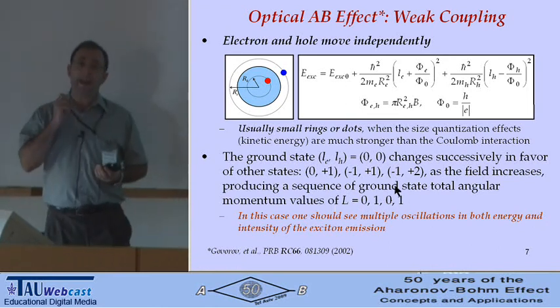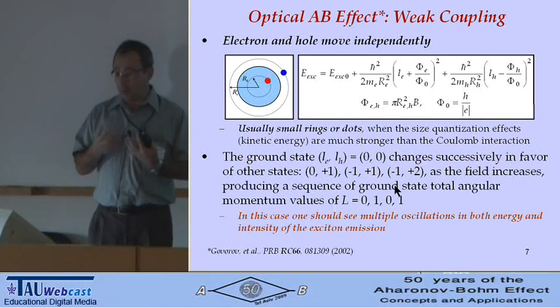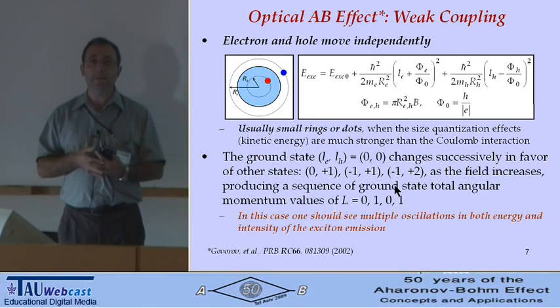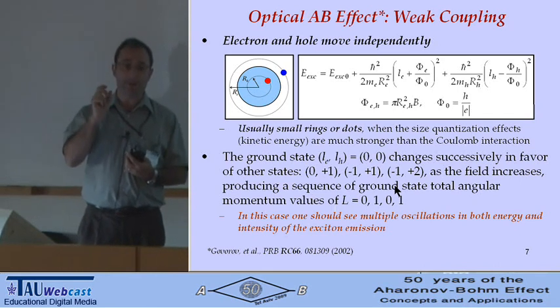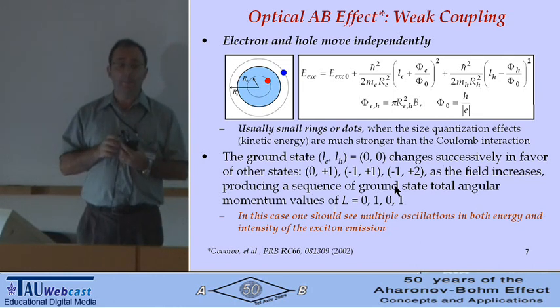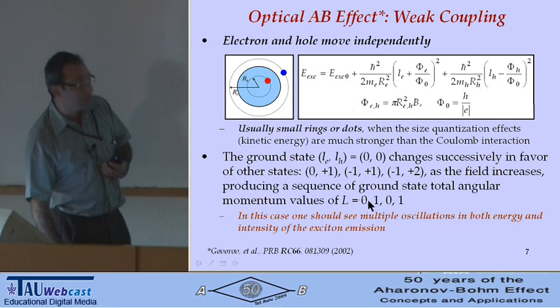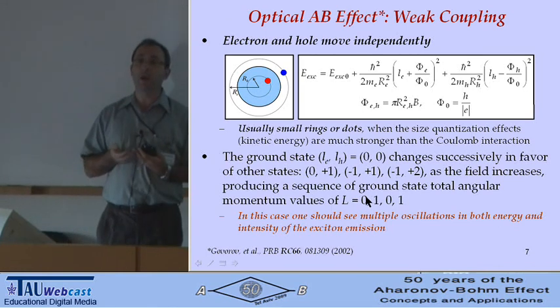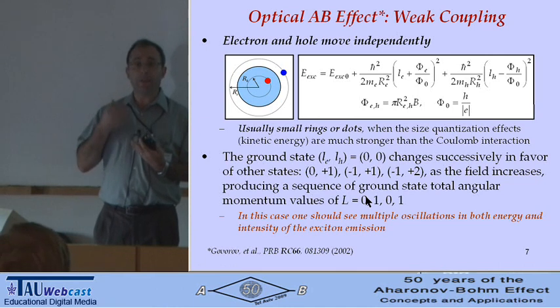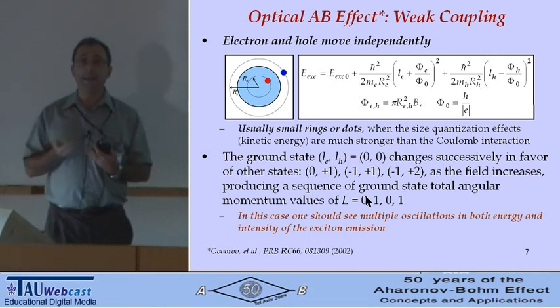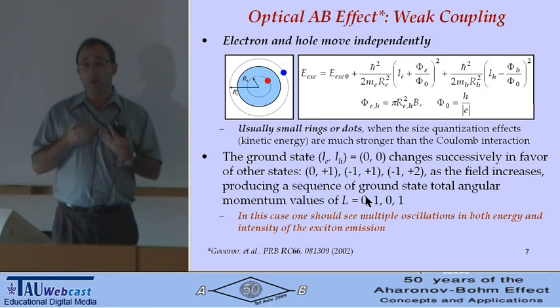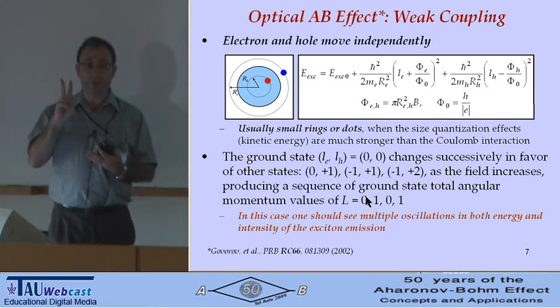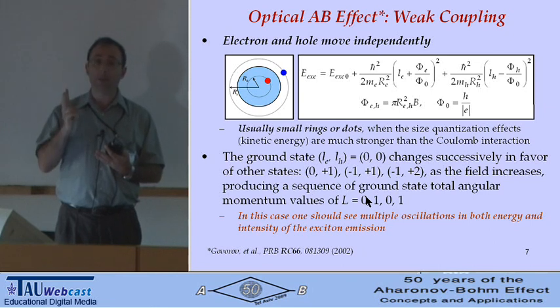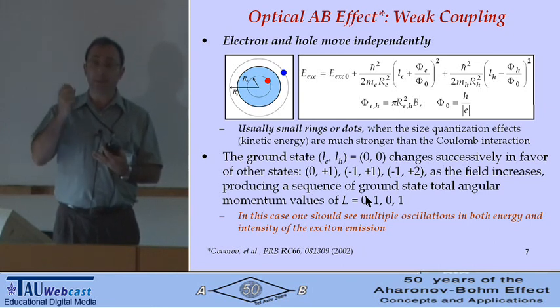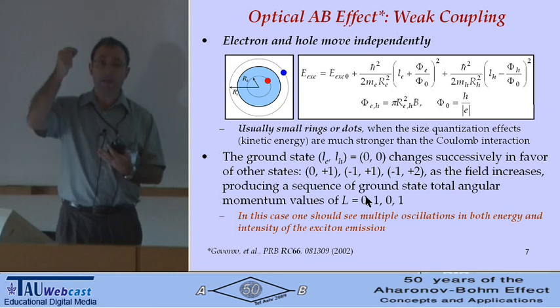Because usually when we look at the energy oscillation in the Aharonov-Bohm oscillation, it's kind of self-evident. However, in a semiconductor, in an optical transition, another effect appears, which is not so obvious for those who don't do this. Because if you change the total orbital momentum from 0 to 1, you have a selection rule that forbids your optical emission. So in addition to the oscillation in energy, you expect oscillation in the intensity of your photoluminescence. So to show that you really have this effect, you have to have two things. You have to have energy oscillation in the excitonic emission, but secondly, you have to have oscillation in intensity. So you have to have bright and dark exciton.